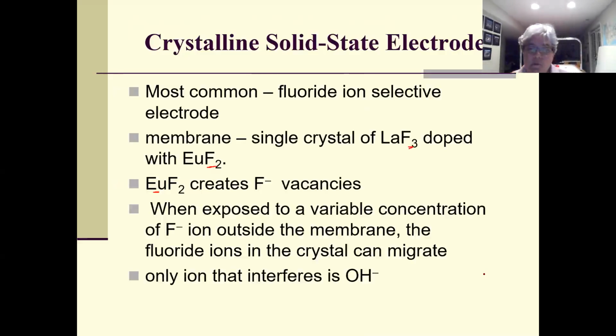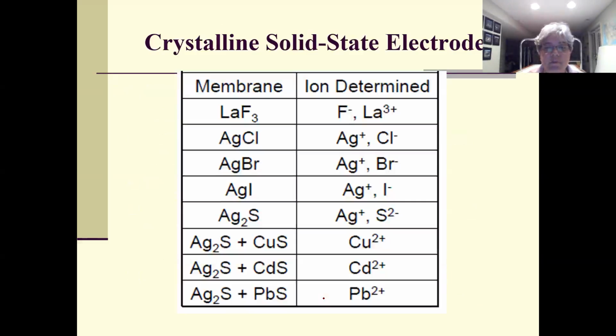This is pretty selective. The only thing you have to worry about also causing a response is fairly high concentrations of hydroxide. So if your concentration is more than 0.1 molar, that will interfere. And that's a pretty high concentration. So quite selective. Okay, so this table just shows you some of the different solid state electrodes. So we've talked about lanthanum fluoride, and it will respond to fluoride, but notice it also responds to lanthanum.